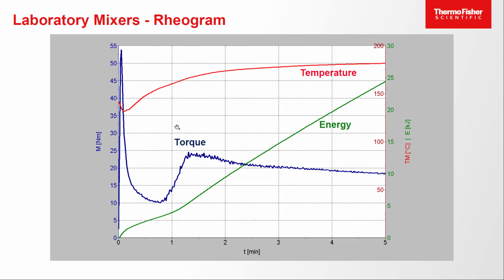Here we see a typical mixer rheogram of the fusion of a PVC dry blend. The test starts with a significant increase of the torque. That's the blue line where it rises in the beginning, when I force my PVC sample, my PVC powder, into the running mixer. Now the powder is distributing inside of the mixer chamber. Some additives like waxes and processing aids are already melting. Therefore, the torque comes down to a minimum, and then starts rising again. What happens here is that the material starts to agglomerate and starts to build up areas of molten or fused material.